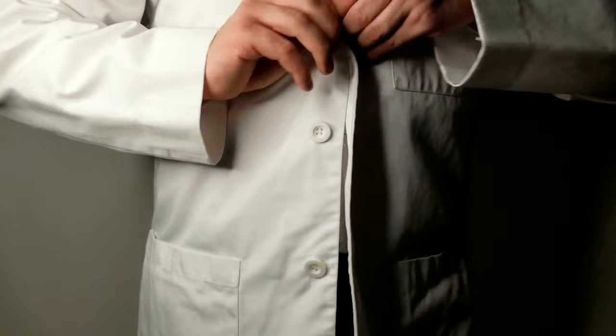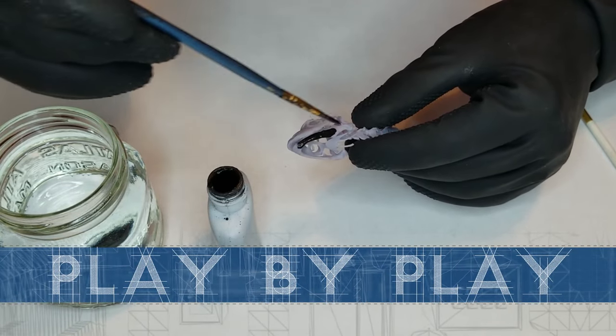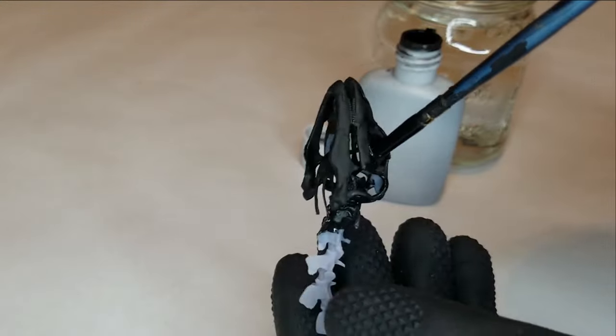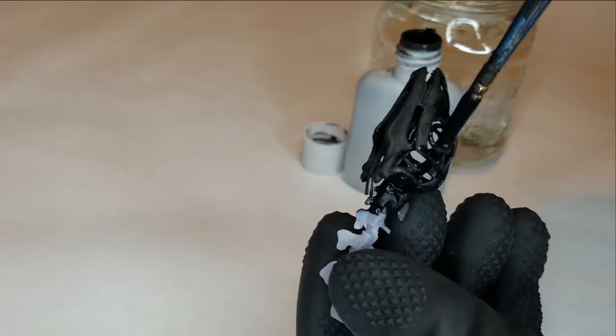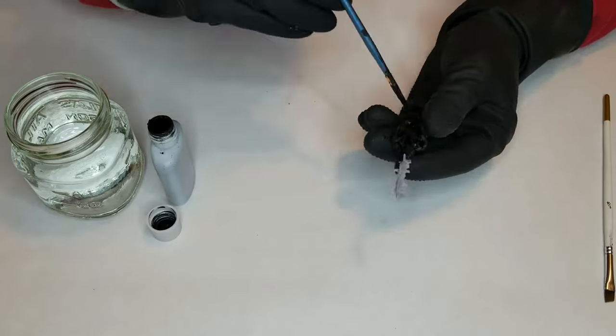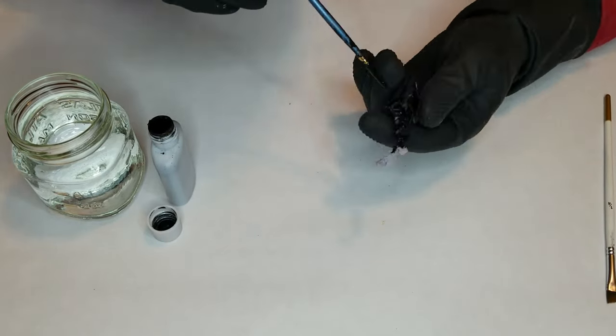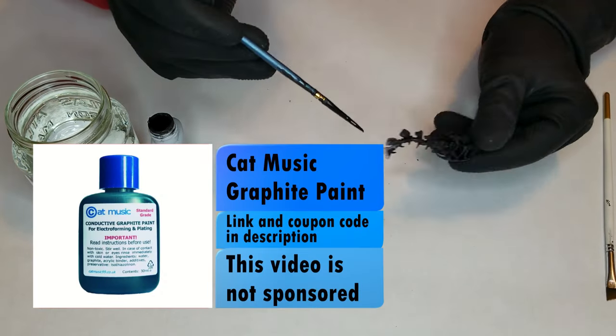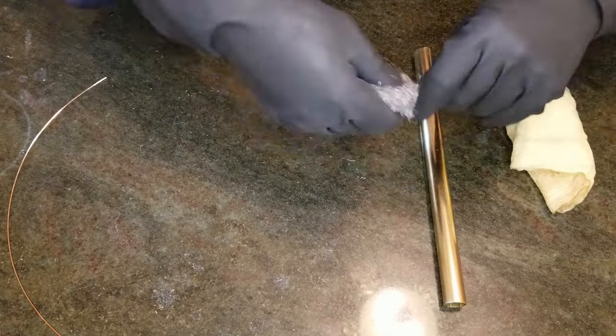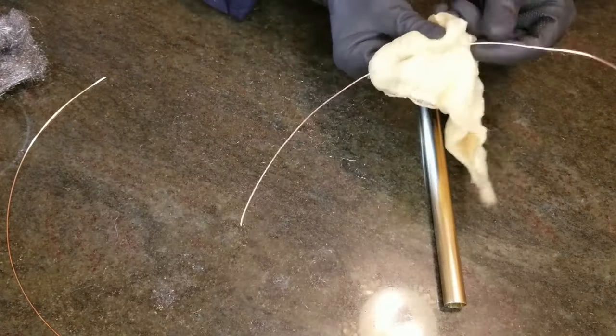Game day 2.0. I was determined to make it work this time, and nothing was going to stand in my way. I applied my graphite paint with a small brush. An airbrush would have produced a smoother, more consistent coat, but it also would have missed many of the nooks and crannies of the skeleton. I really don't mind a little texture either, since that only makes it look more like real bone. I considered making the graphite paint myself, but being new at this I wanted to minimize the things I could mess up. Even so, I had to try a few different brands before I found a paint I was really happy with. To maximize conductivity, I first scraped off the wire's patina with some steel wool and tack cloth.